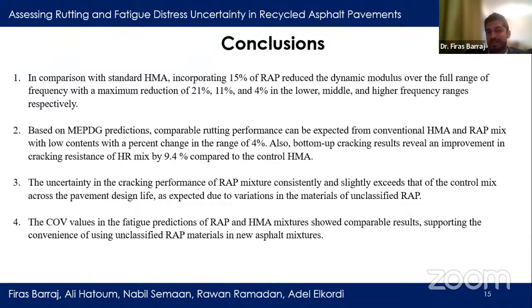Thirdly, the uncertainty in the cracking performance of RAP mixtures consistently and slightly exceeds that of the control mixes across the pavement design life, as expected due to variation in the material of unclassified RAP. And finally, the coefficient of variation value in the fatigue prediction of RAP and HMA mixtures showed comparable results, supporting the convenience of using unclassified RAP material in a new asphalt mixture.